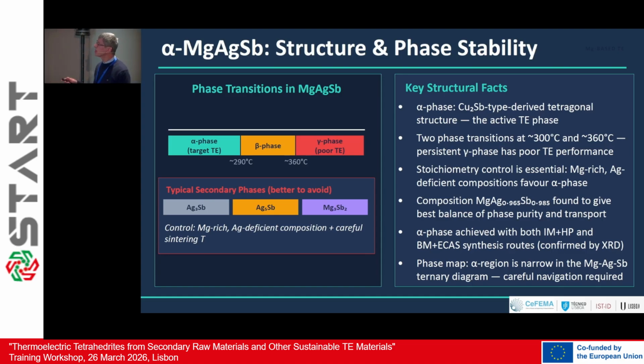So the stoichiometry control is really essential, in particular playing between magnesium and silver, which is really important to get the proper material for thermoelectricity. This is actually not exactly the best composition. This is silver 0.97 and antimony 0.99 something, okay? So it is a little bit less than one silver there. And actually, there is a narrow zone in the phase diagram where it is possible to prepare the proper samples.